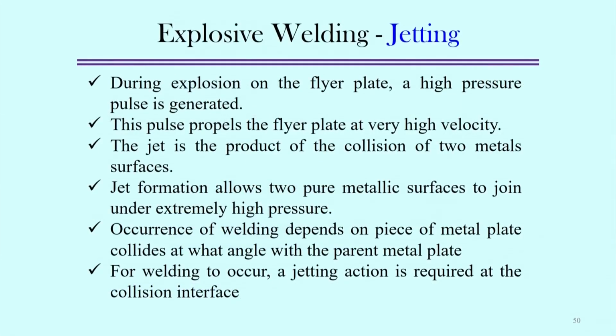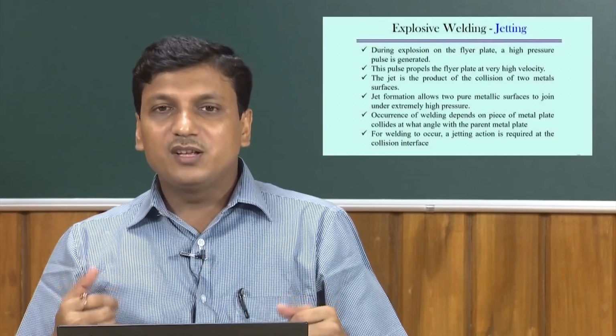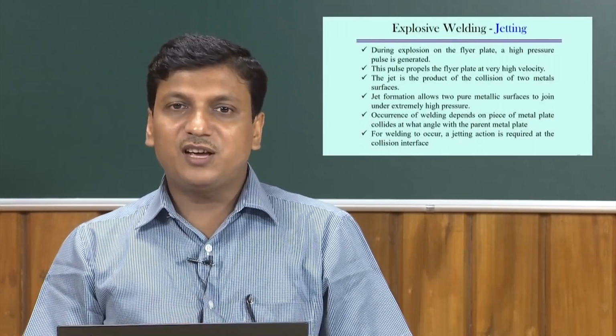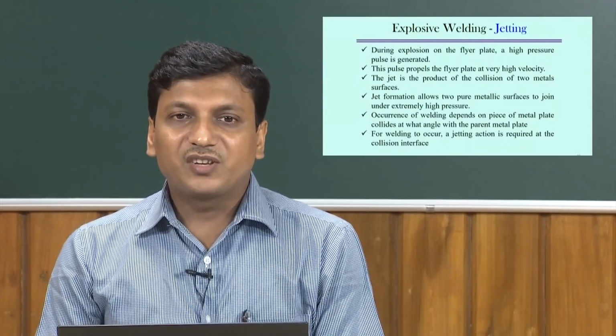Let us look into the other aspects, the most significant aspect of this joining mechanism observed in explosive welding, that is called jetting. Jetting means that during the explosion a high pressure pulse is generated on the flyer plate, and this pulse propels the flyer plate at a very high velocity, and the jet is then produced by the collision of the two metallic surfaces. The jet formation allows the two pure metallic surfaces to join under extremely high pressure. That high pressure pulse generated during the explosion is responsible for the creation of the jetting.